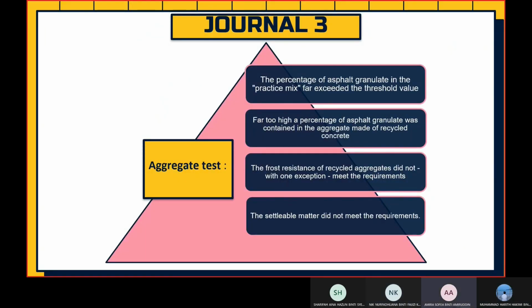The percentage of asphalt granulate in the practice mix far exceeded the threshold value. Second, there was far too high a percentage of asphalt granulate contained in the aggregate made of recycled concrete. The third is that the frost resistance of recycled aggregates did not, with one exception, meet the requirements. And lastly, the settleable matter did not meet the requirements.